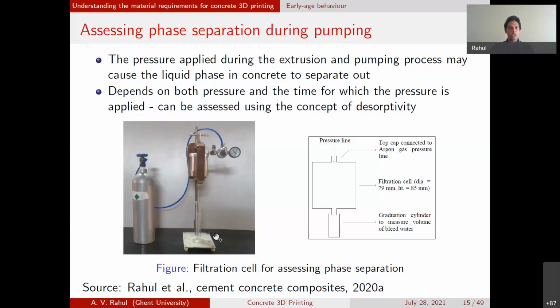Now, one thing that you should note here, particularly with phase separation, is that it's not just the amount of pressure that you apply that dictates the amount of water that comes out during this test. If you apply a high pressure, you will see maybe a higher amount of water coming out, but it also depends on the duration for which you're doing this test. If you apply pressure for a longer time, initially a small amount of water comes out, but as soon as some critical time is exceeded, a larger amount of water starts coming out from the concrete. So the amount of time for which the concrete is subjected to this pressure is also critical. This is something that we need to take into consideration again, especially if you're using a piston pump.